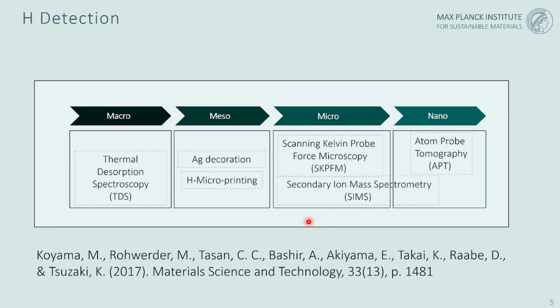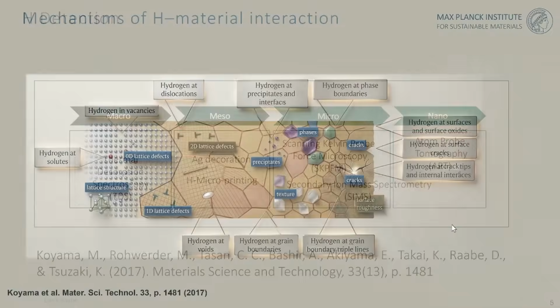Furthermore, SIMS techniques are also affected by the secondary ion direction. That means you might want to repeat measurements by rotating samples about their normal directions, for instance. And at the near atomic scale, you can use atom probe tomography, but like with SIMS methods, it is advisable to use deuterium to make sure that the hydrogen that you measure is not acquired hydrogen from the chamber or from transport, but really the one that you used for charging.